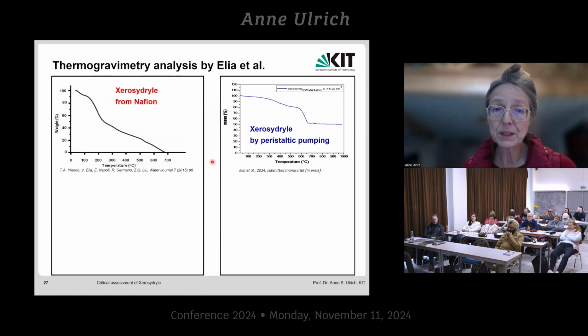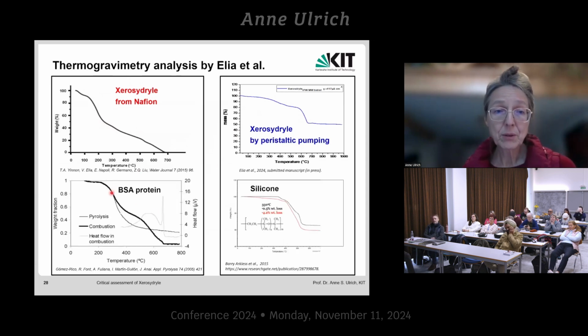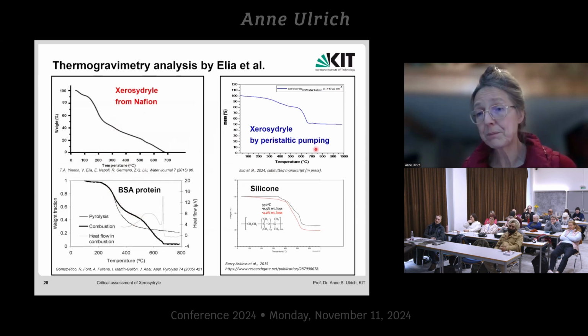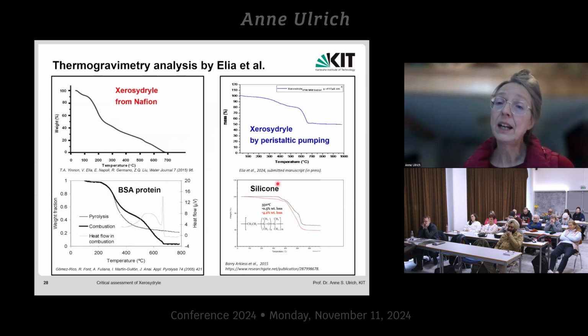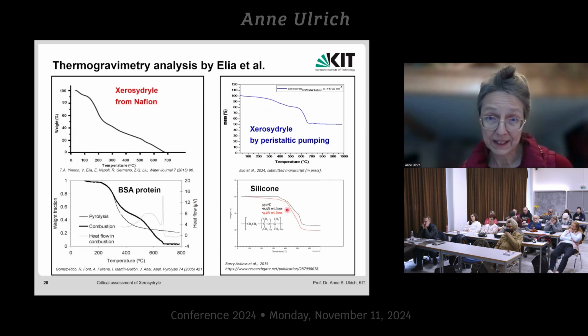And interestingly, when we looked into the literature, a protein spectrum of bovine serum albumin, a standard protein, has a very similar structure to the contaminated sample from Xerosydryle made by Nafion. You see these two. And in the case of peristaltic pumping, we are pretty sure, just looking at the literature spectrum of silicone, that silicone has rubbed off from the peristaltic tubes. This is a known phenomenon. It's actually a known problem in the pharmaceutical industry. And so the silicone itself gives a different thermogravimetric analysis to the protein, but that was also found for the Xerosydryles from different origins. So I think that can explain really everything.